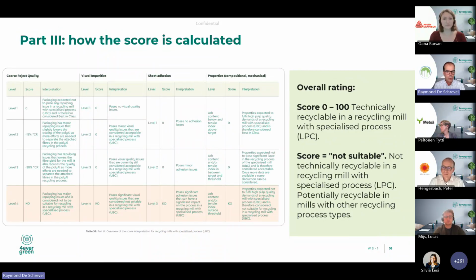Again, the overview of the parameters and how they score, slightly different from the other tools, because you see here a line between white and red. Within part 3, there is no gaining points or deduction of points. It's either good or it's bad. And here, maybe we had some slight advantage of starting a bit later, where the PPWR was already more advanced, and we could use the influence of the professors of that work. I also did a gap analysis here, that we try to stay as close as possible to the performance scoring of the PPWR. So we have also what the others have, scoring from 0 to 100, but also a not suitable. The scoring itself is different. So you have either 0 points when you are okay, and you have a knockout when you're not okay.